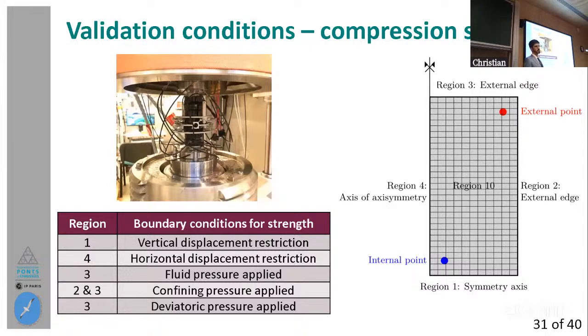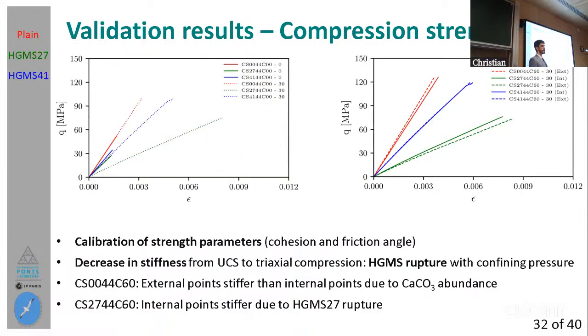There I have again the same geometry, of course, but the difference is the conditions in which I have applied confining pressures in regions 2 and 3. Then I have fluid pressure and deviatoric pressure applied in region 3, which corresponds to this part of the machine. With this, I have obtained some results of deviatoric stress against strain for different conditions. I have to mention that these results were obtained with the calibration of the parameters that I have shown you before, cohesion and friction angle.